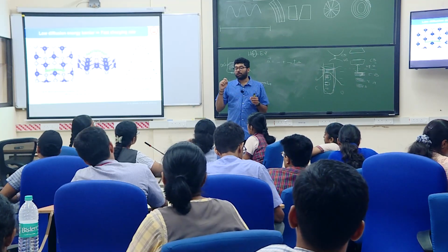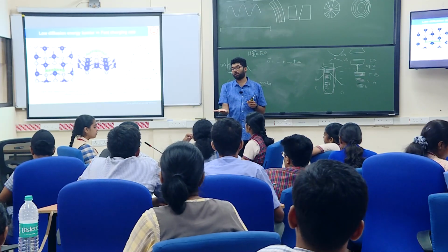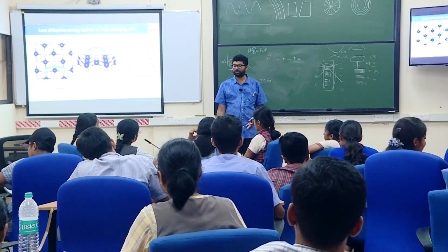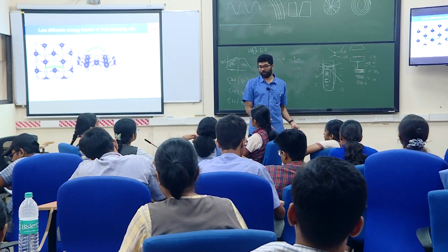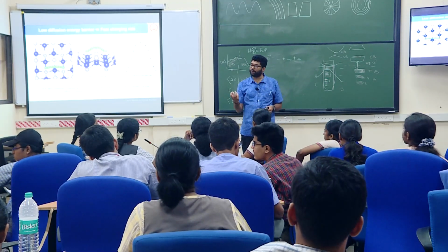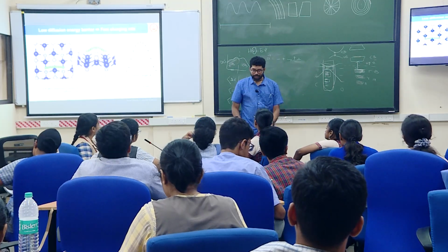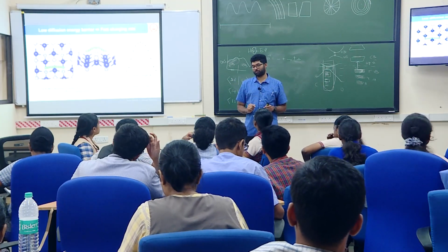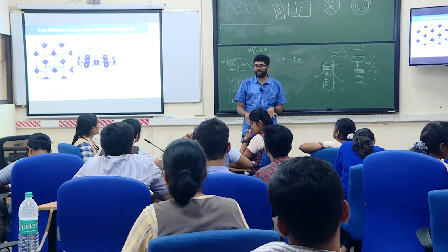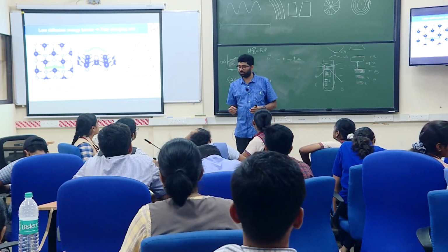The counterintuitive thing here is that potassium is the one that is binding strongly to the system. What we would generally assume is if something is binding strongly to the system, it will not be moving at all, right? It will be strongly held there. What I am trying to show here is even when it is strongly bound, it can easily move to the next one provided the adsorption energy difference between this site and the next site is less. Then what is the barrier for me? I just need to move a little bit only.